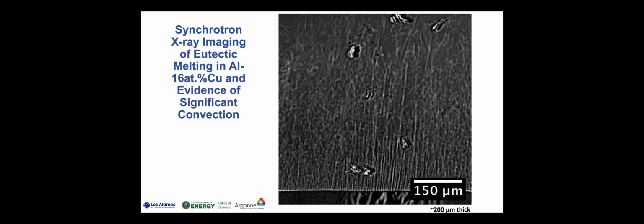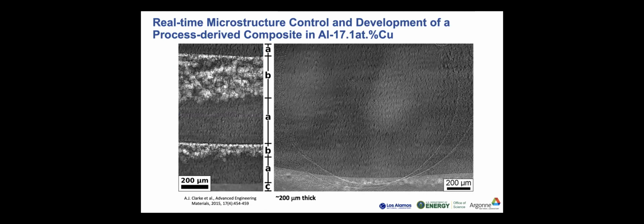Taking that a step further, we actually decided to do a neat demonstration of real-time microstructure control through the development of a process-derived composite. This is now an aluminum 17 atomic percent copper sample. And so basically what we have here is a solidified eutectic, again, one of these lamellar eutectics. And what you're going to see is this melting and solidification cycling. And you'll see the way that microstructure develops and that we're able to control it.